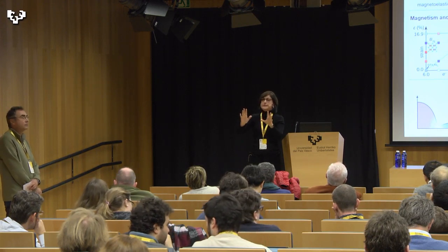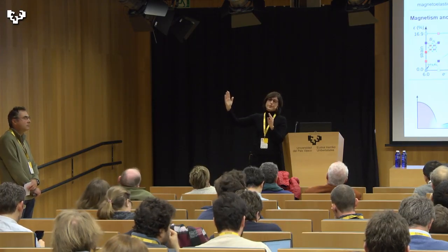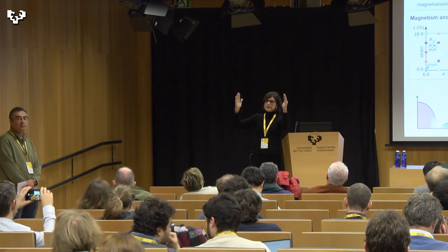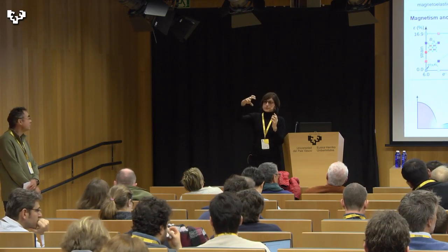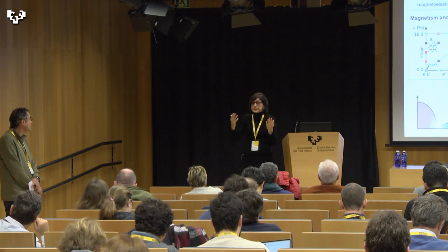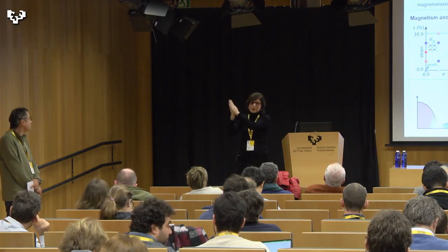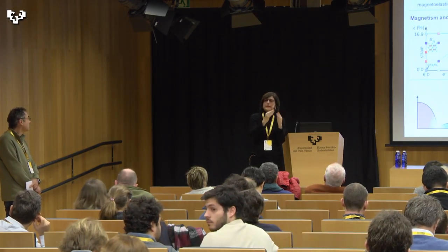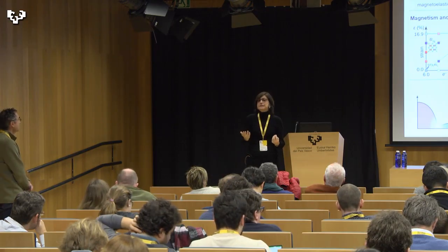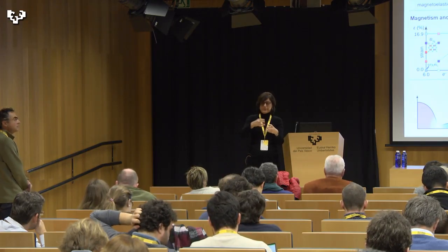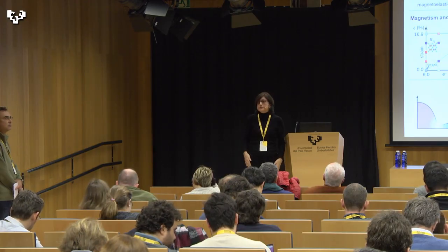Okay, so the observation is indeed that they have done experiments on various doping samples, and you go from this nematic, this B2G, to the B1G, but by a region where, so this nematic is what we call an Ising nematicity, basically, because it's basically plus minus. So there is a region where it's not anymore Ising, when you are transforming from this B1G to this B2G by just applying the doping. The way we did that in the simulations, either you have to do very big supercells, or you apply this virtual crystal approximation where, not taking into account the doping, you substitute your atoms by an artificial atom that has the doping that you want.